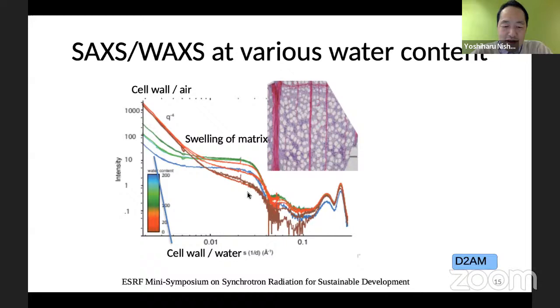Now, what happens here in this Q range, which is related to the cellulose microfibril and the matrix component contrast, is that water does not penetrate cellulose crystals, but it is swelling the matrix component, and so the contrast between the crystal and the matrix increases. So when it's in a wet condition, we see an increase in intensity in this region. And also we will see that the separation between the crystals increases from the shift of this shoulder.